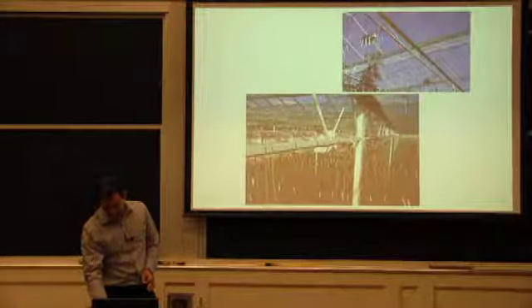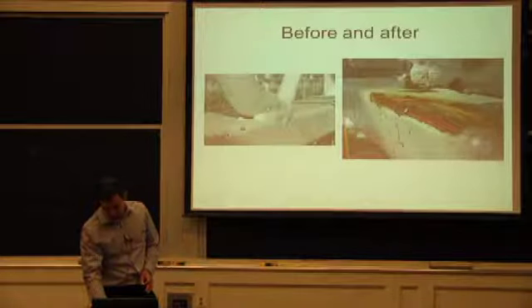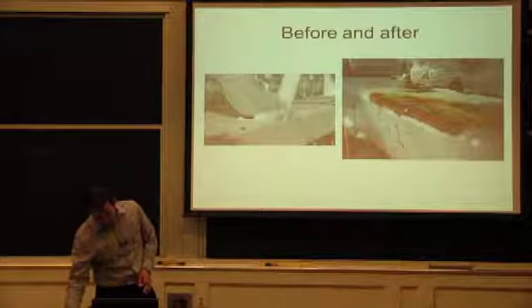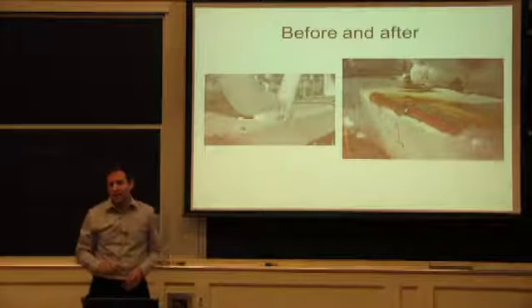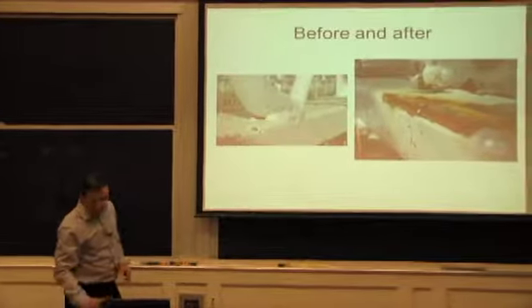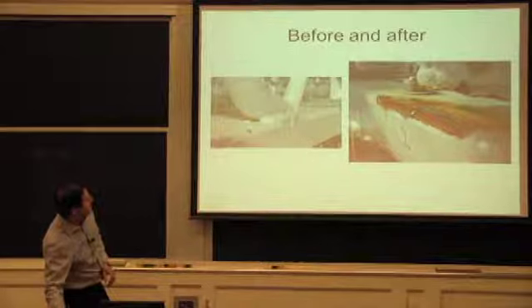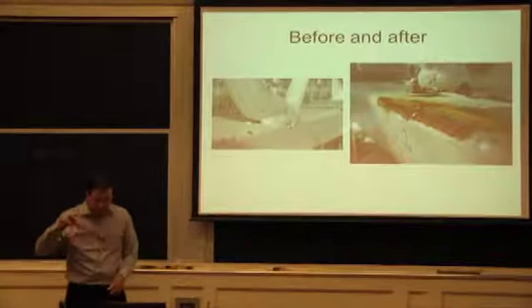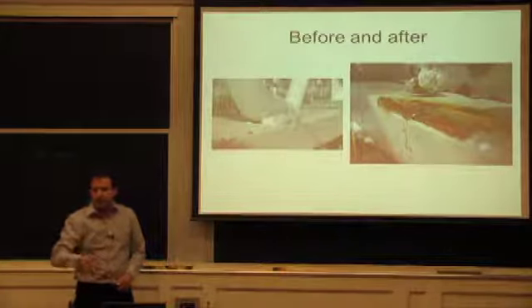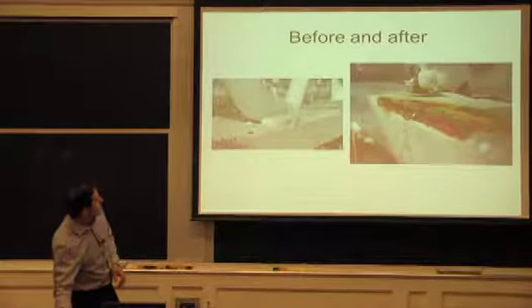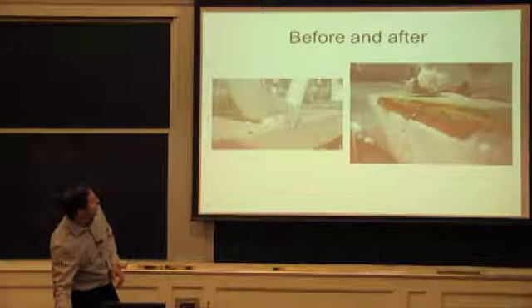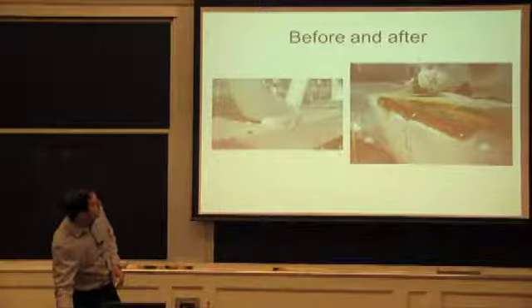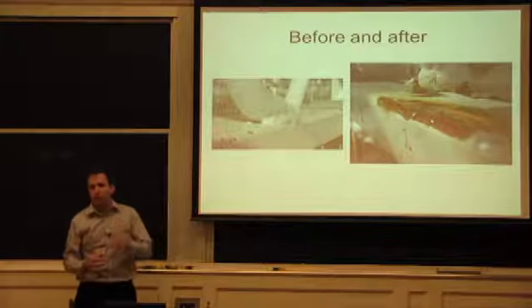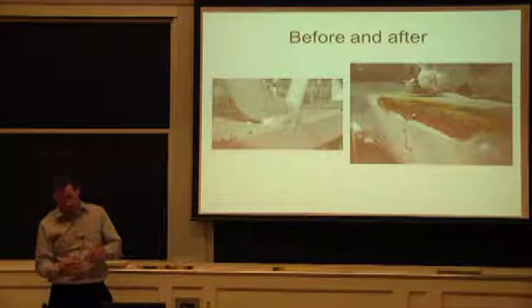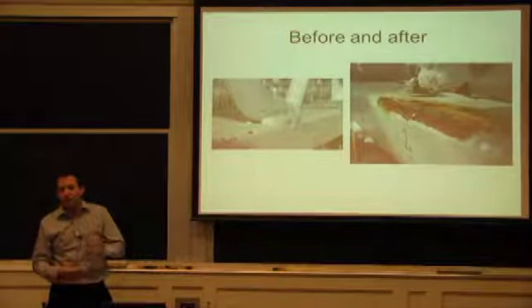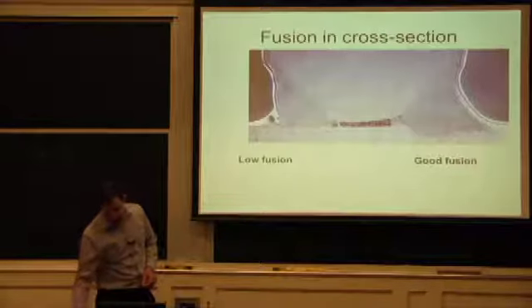That's a big warehouse for tomatoes, a greenhouse, that I worked on. And same story where you look at this weld, and we talked a little bit about convexity. So maybe today if you go somewhere and you see this, you'd be able to say, oh, this looks like it's a little sort of deposited on the surface as opposed to being really weld fused. It has a low contact angle here, and this is the same type of weld that after the fact you can see just pull off from the surface of that chord, as opposed to ripping the metal apart with it.